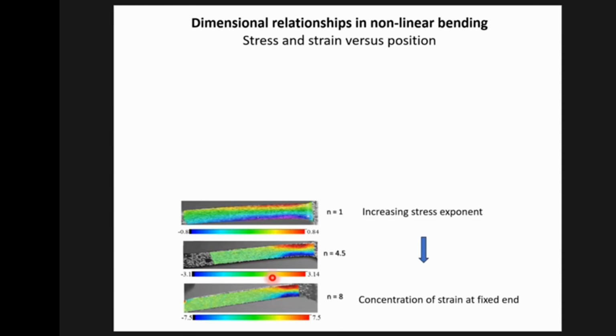Given that, I will use strain loosely. It's really strain rate, which is proportional to stress raised to some power. The distribution of strain tends to be highly localized with respect to stress, because if I halve the stress, the strain rate will drop by a factor of 64. So if I have a cantilever like this, and I go to the middle of the cantilever, the stress is dropped by a factor of 2, and my strain rate will have dropped by a factor of nearly 2 orders of magnitude, if I have a stress exponent of 6.